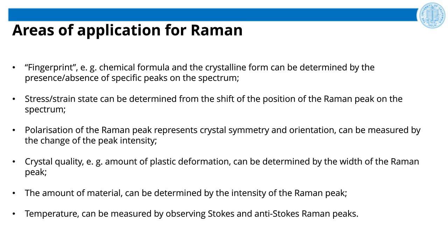Raman is also sensitive to the stress-strain state of the materials, and that can be determined by the change of frequency of the Raman peak. In other words, the shift of the position of the peak is representative of the stress-strain state of the material. Then polarization of the Raman peak is representative of the crystal symmetry and orientation and can be measured by the change of the peak intensity, its height. We can also rate crystal quality or amount of plastic deformation, which can be determined by the width of the Raman peak. The amount of material can be determined by the intensity of the Raman peak, while temperature can be measured by observing the so-called Stokes and anti-Stokes Raman peaks. So it's quite a powerful technique.